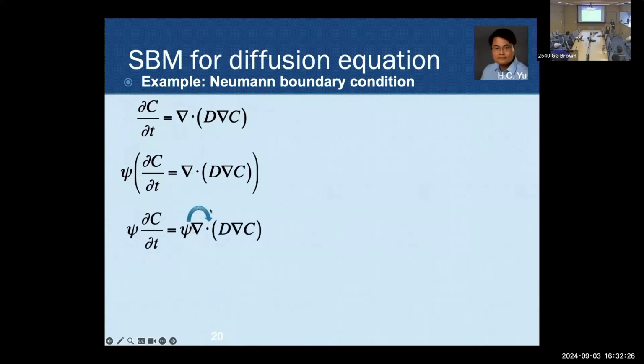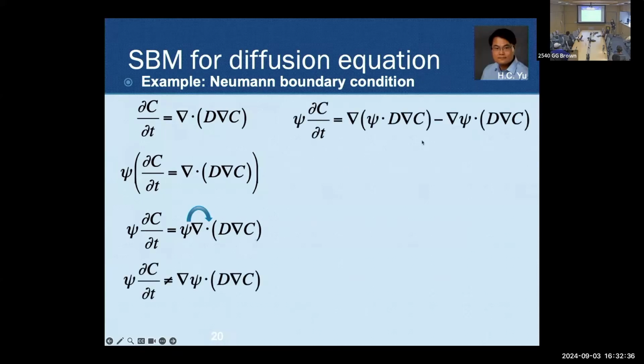One thing you want to do is get this psi inside of the gradient operator. You can just put it in there, but you have to apply the chain rule, or product rule of differentiation, and you get this extra term that comes out. Make sense? Then you make a note: psi is 1 inside of where you want to solve the equation, and grad psi is 0 there, because the gradient of a constant is 0. So this goes away, and you recover this equation inside of the domain.